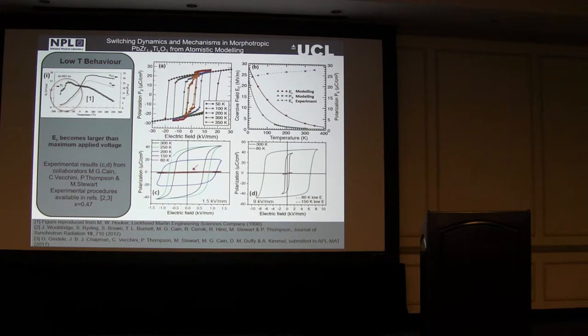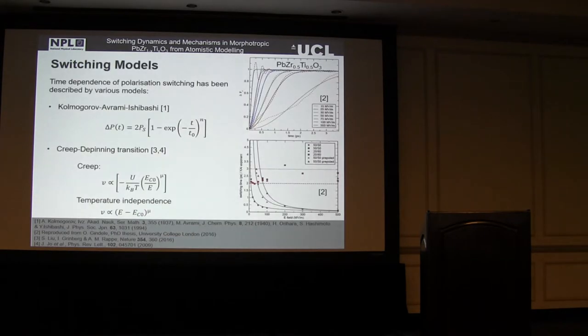Like I said, low temperatures. This hasn't been particularly well characterized for the morphotropic phase boundary. This is one of the things we started looking at. We found quite an interesting report by NASA where they found that the coercive field drops off at about 200 Kelvin. And at about 300 Kelvin, the saturation polarization starts to drop off, going pretty much to zero. But when we did our model, we found that actually the coercive field would keep increasing and have its maximum at zero Kelvin. We wondered what the discrepancy was, but our collaborators repeated the experiment and found the same thing, where below 200 Kelvin the hysteresis became extremely narrow and the curve started looking odd. That was using one experimental setup. They then used a different experimental setup where you could apply a larger voltage, and they found that you would actually get the hysteresis. This is quite an important point. If you get the coercive field to drop off, it could be that the applied voltage is too small to overcome the coercive field.